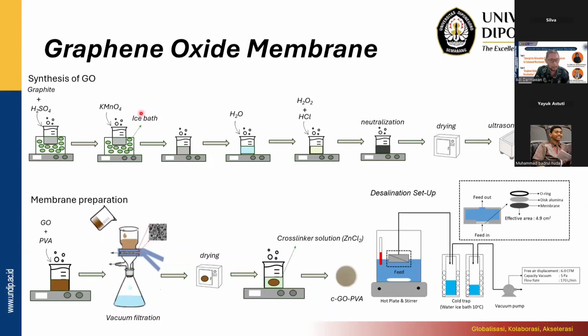Okay, the idea is we have graphite and we have to oxidize the graphite using strong acid, sulfuric acid, and permanganate, yeah, permanganate. And after that, we got the graphene oxide. And the graphene oxide, next, we mix with the PVA, polyvinyl alcohol, and cast the GO and PVA mixture, and put it with this crosslinker.